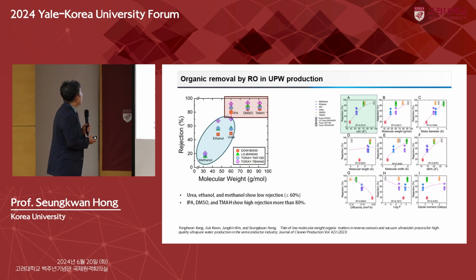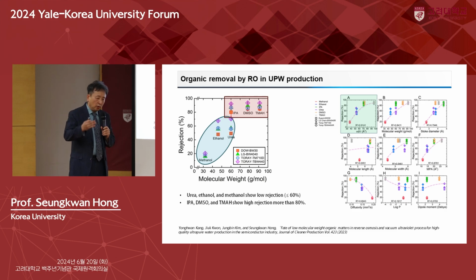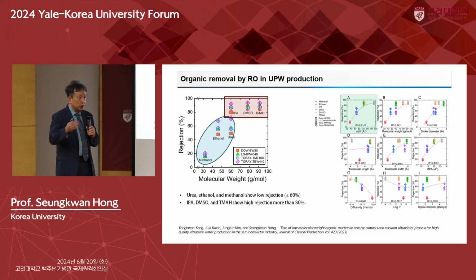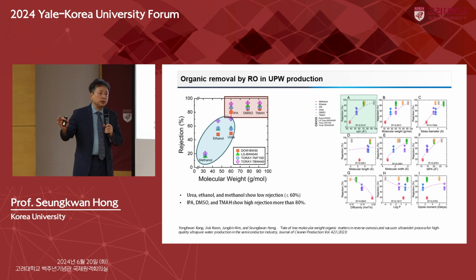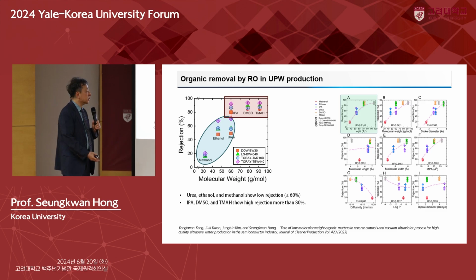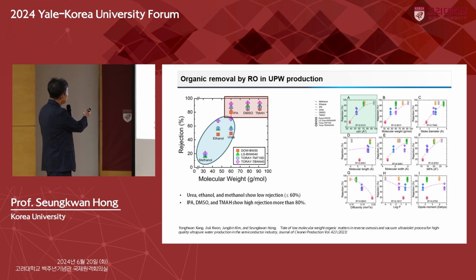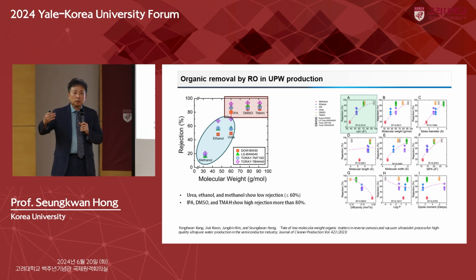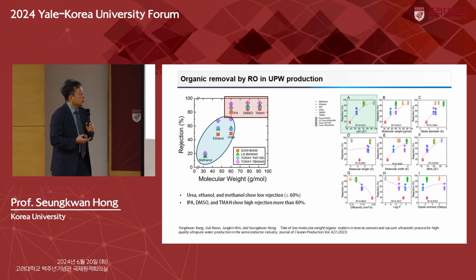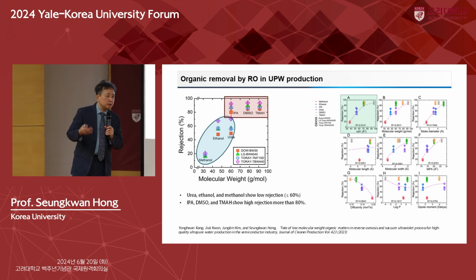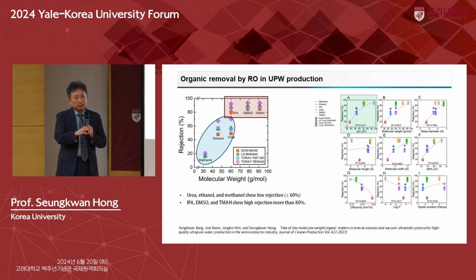So what we did in our lab was to verify the fate of those low molecular weight organic molecules. We conducted experiments with RO. For example, here we got membranes from major companies like Toray, LG Chem, and Dow Chemical. As you see, methanol, ethanol, and urea are rejected at less than 60%. IPA, DMSO, and TMAH are rejected at the level of 80 to 90%. Not good enough. RO is designed to reduce the salinity, the TDS level of your water, but as far as low molecular weight organic matter is concerned, it is not effectively removed by the RO process.